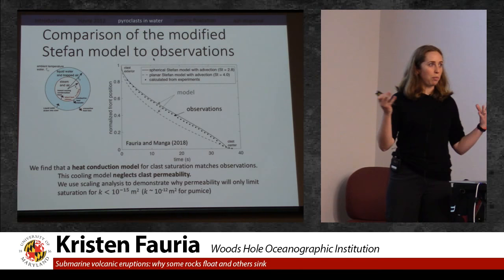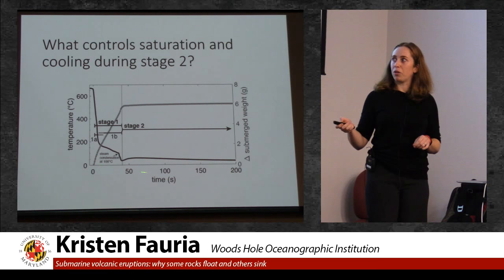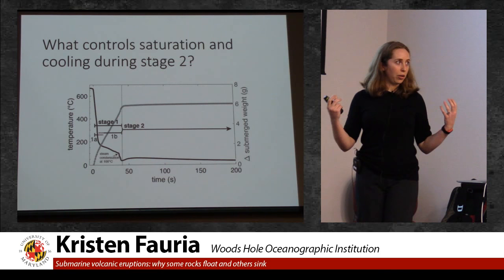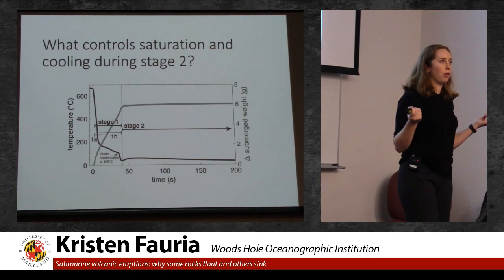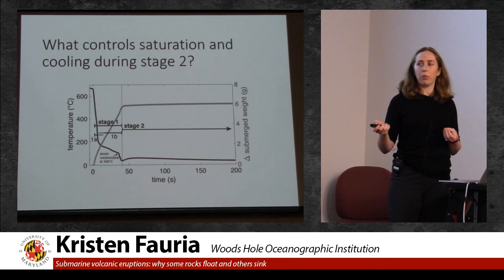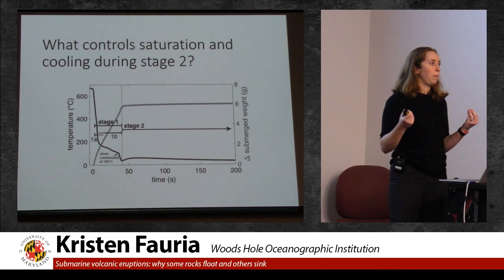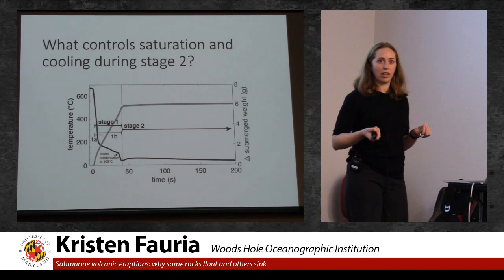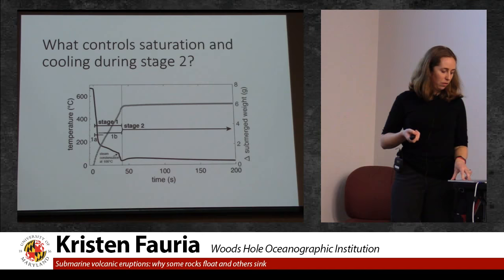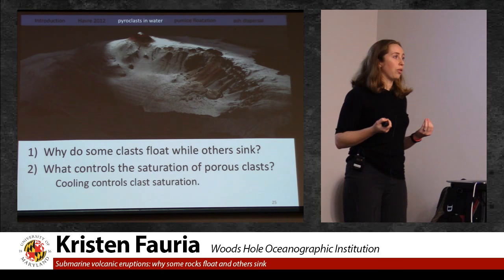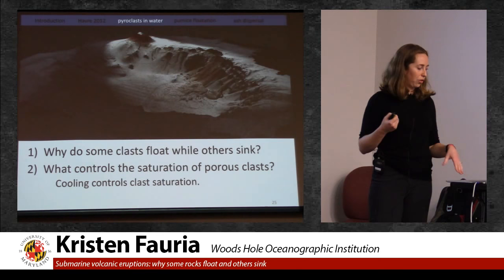But briefly, I just want to bring you back to this figure where we have the first stage where cooling is really limiting saturation. And then you have the second stage. And using some additional modeling, I won't show you all the details here, we concluded that thermal conduction is again responsible for cooling during the second stage and that the clasts saturate due to thermal contraction of any residual trapped gas inside the clast. So going back to the first two questions, number two, what controls the saturation of porous clasts? Well, we found that it's the cooling that controls the saturation.